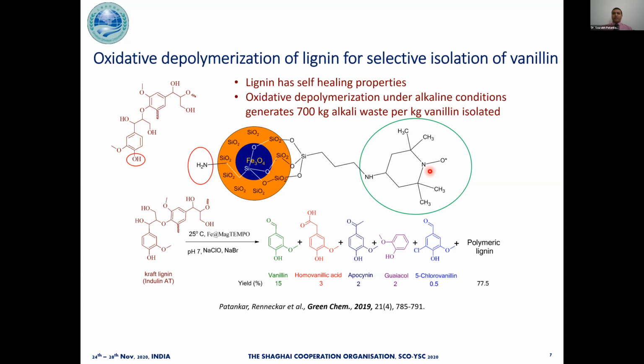The traditional oxidative depolymerization of lignin is done in an alkaline environment, and the process results in around 700 kg of alkali waste per kg of vanillin isolated. And so I was able to do this reaction at neutral pH using hypochlorite as the primary oxidant. And I was able to get around 20% yield of vanillin and associated compounds, high value phenolic monomers from kraft lignin.